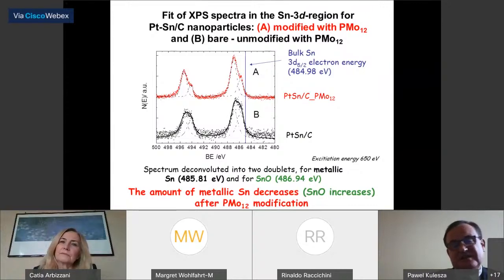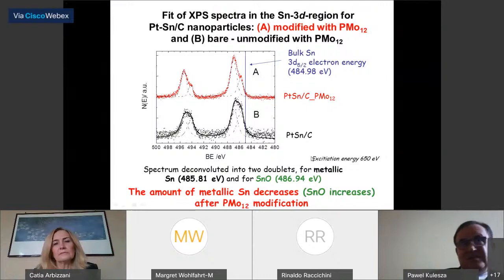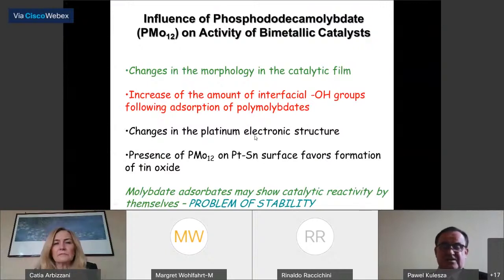Platinum also breaks the C-C bond. Now we see clearly from this that we have more tin oxide once we modify the system with polyoxometallate. So tin oxide is actually active in removing the poisons. So changes in morphology, basically speaking, we still cannot exclude interactions of polyoxometallates with platinum, but there is a problem of stability.